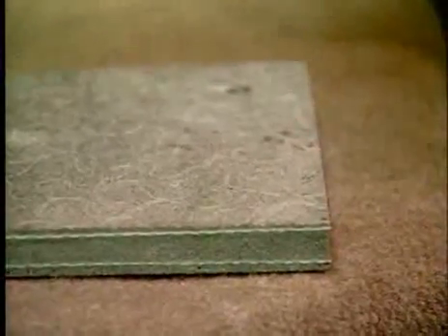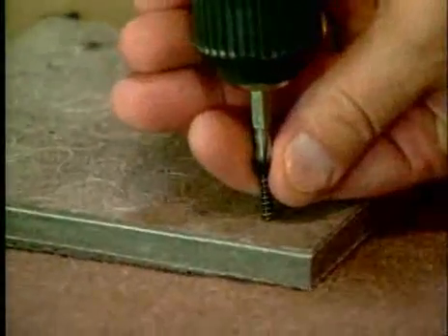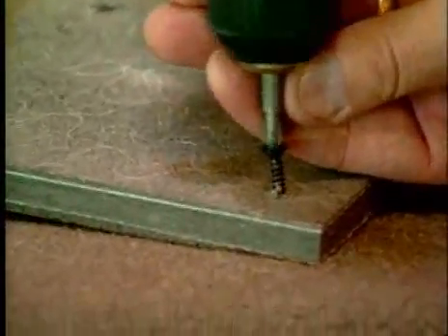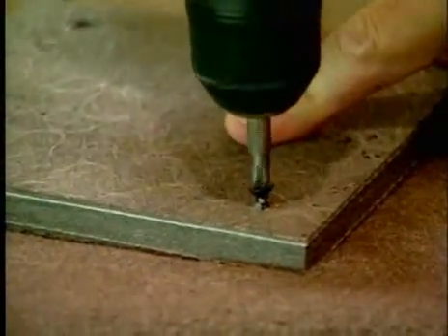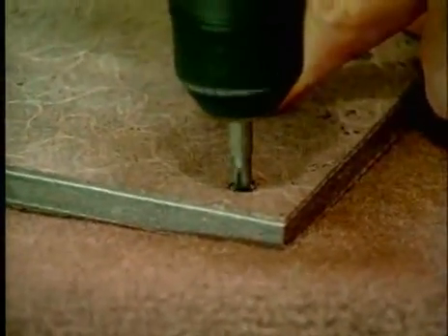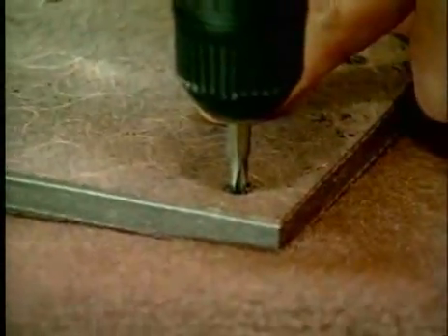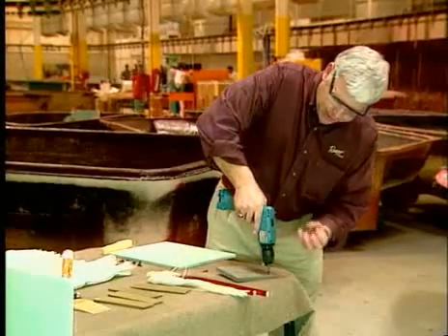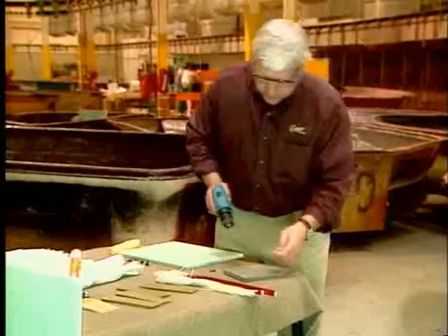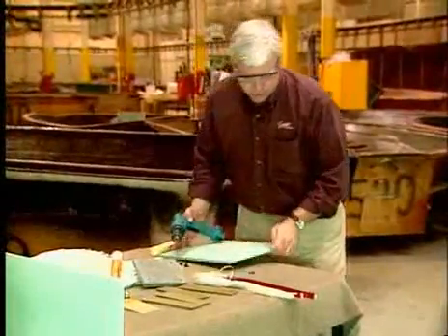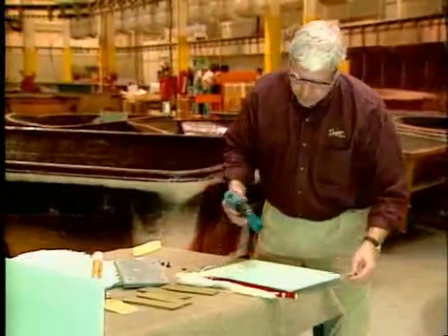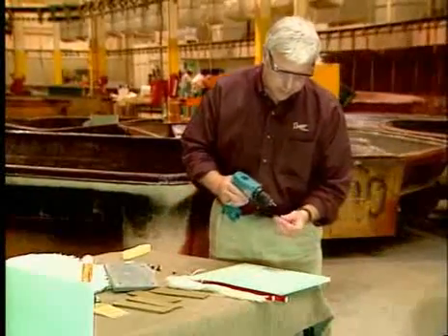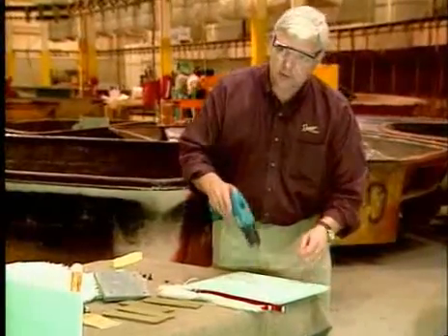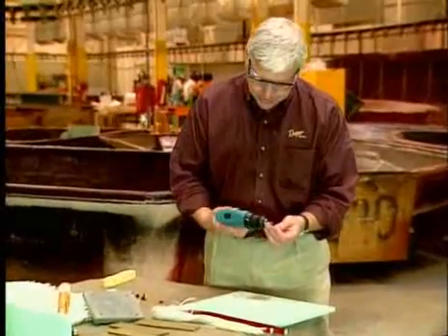Let me show you some of the widely used materials on the market that we incidentally don't use. Let me show you how a screw goes into that material. This is without a pilot hole, so I'm going right into the material, and as you can see, there's no bottom. That screw's actually spinning in the composite because it doesn't have the integrity to hold the screw. On the other hand, take that same screw and run it into a piece of our pultruded material, which is not as thick as that material, but the thickness is really not what we're looking at. We're looking at the structural integrity of the composite itself.